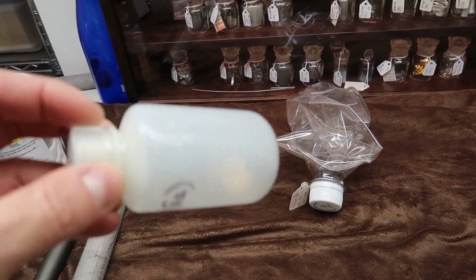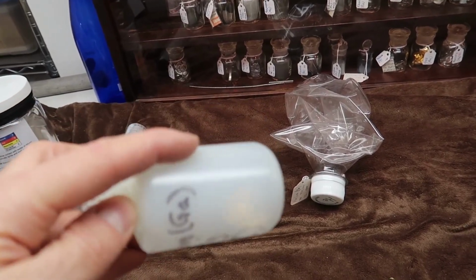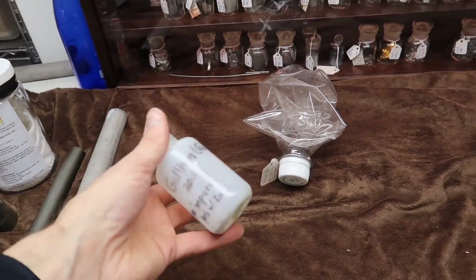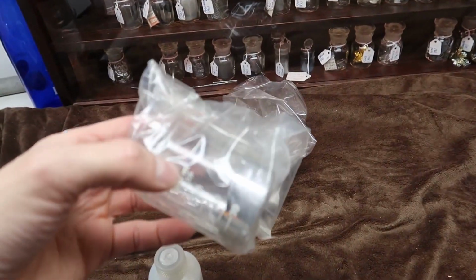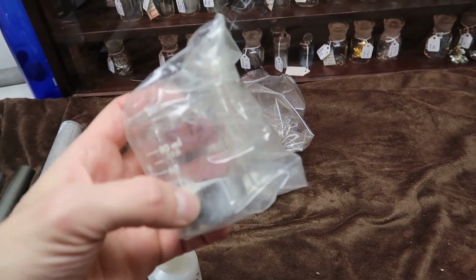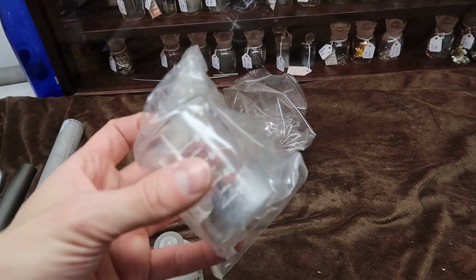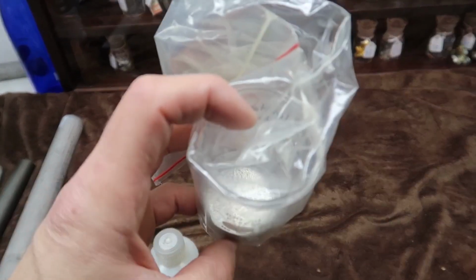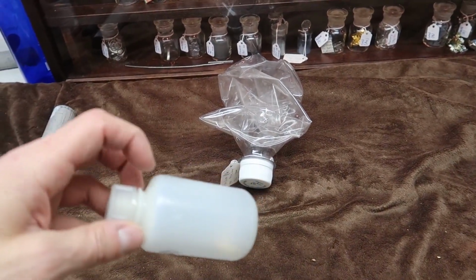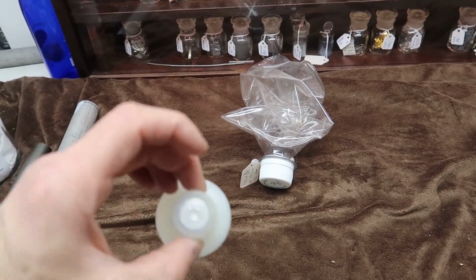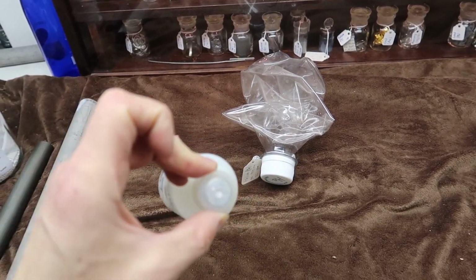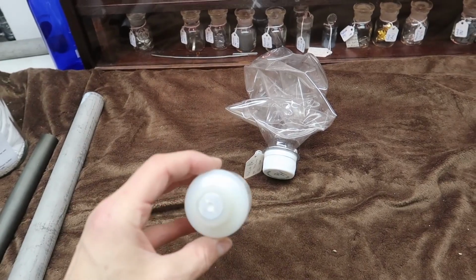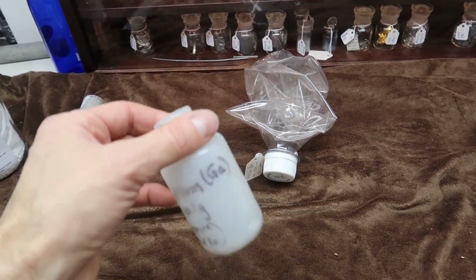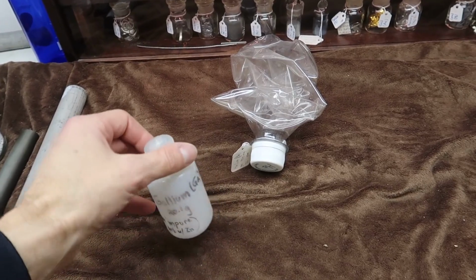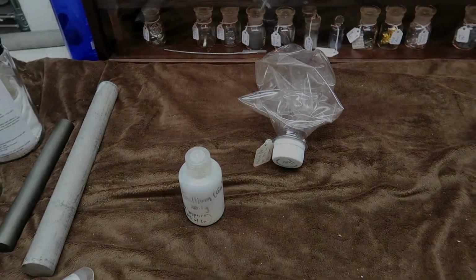And you might think it would be useful for a lot of stuff, but the problem is that it wets a lot of things. If you try to store it in glass, it will wet the glass. Here's a glass jar that was used to make this alloy, and it's still coated with metal inside. Somehow it doesn't coat the HDPE, which is good, except it did coat the top of this lid really well, which must be a different material. It's probably nylon. So it is very selective in what it sticks to, but it does stick to a lot of things. And it's not toxic.